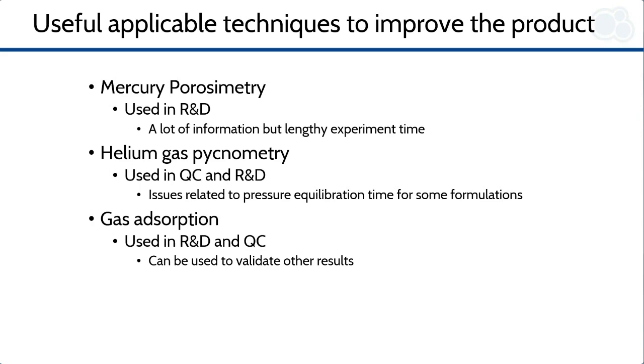This technique is not always suitable for rapid tests during a production cycle because the sample preparation and the experiment are time-consuming. Additionally, extra laboratory safety standards for the presence of mercury and technician training are required for safe and proper use. Gas pycnometry can be a suitable test for rapid determination of skeletal density and does not require a specific lab or expert users. Also, the surface area determination can be performed rapidly, but it still requires the use of liquid nitrogen and some additional expertise.